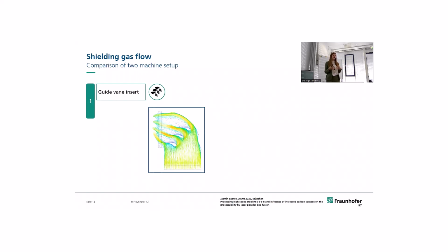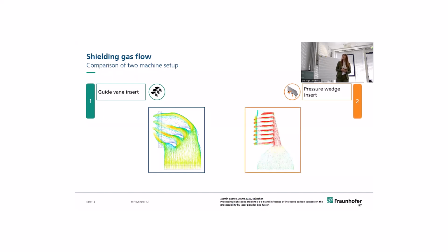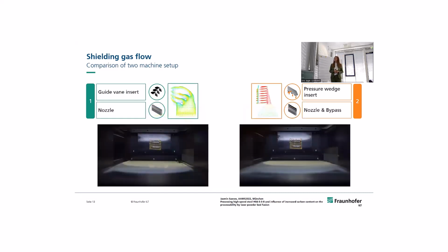But there are two pictures that show why we are doing it, because if you initially have those guide vanes, we see that something is happening here that we don't want. We want a homogeneous shielding gas flow moving along our process chamber. Here we see it's moving up, which might not be very good, and we also have a lot of turbulence here. Looking at the pressure wedge that was developed at ILT, we see a higher speed of the shielding gas flow, first of all because of the narrowing space, and we also see a straight direction over the platform, which should be beneficial for our process. We looked into that with videos.